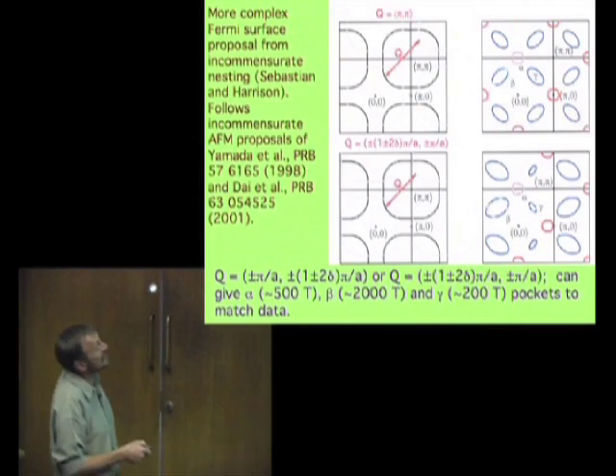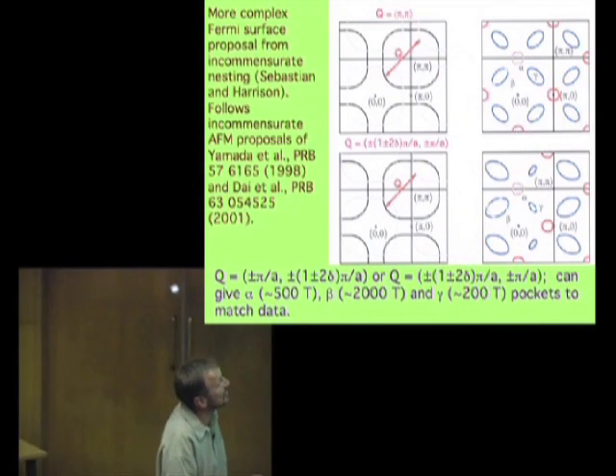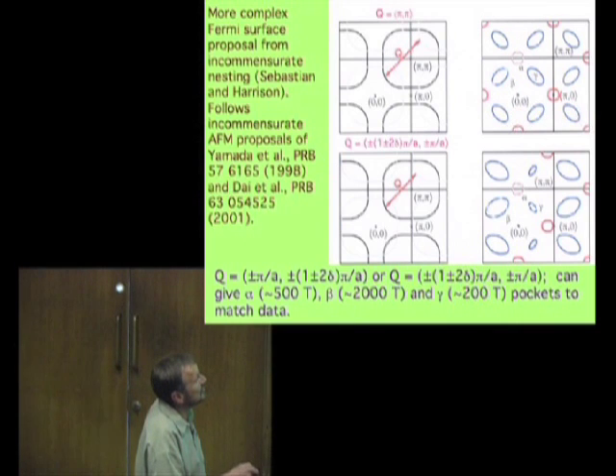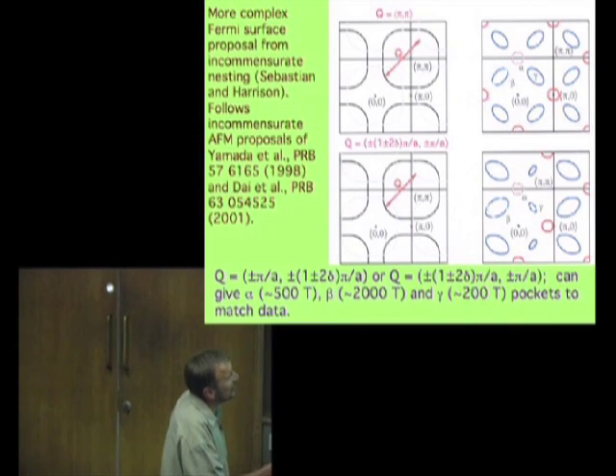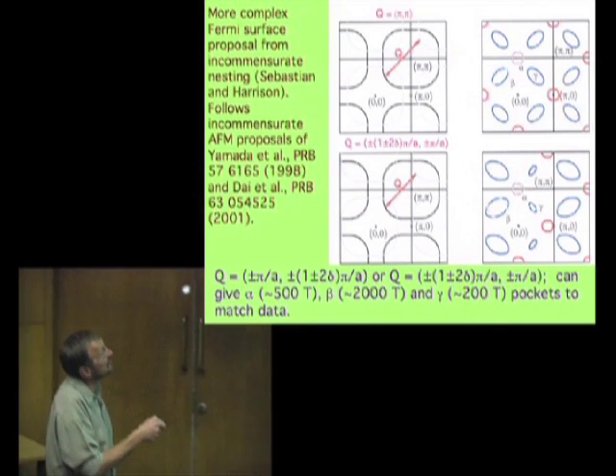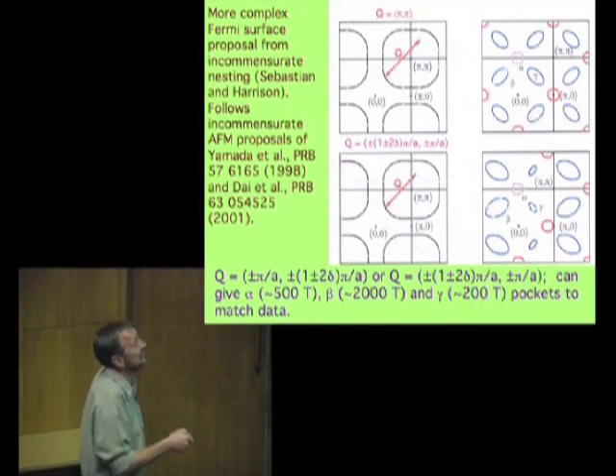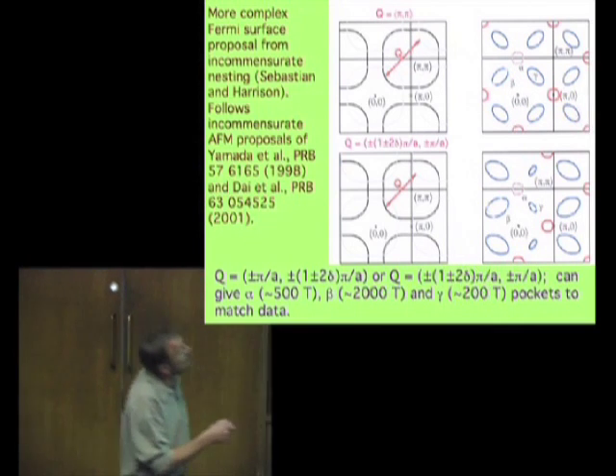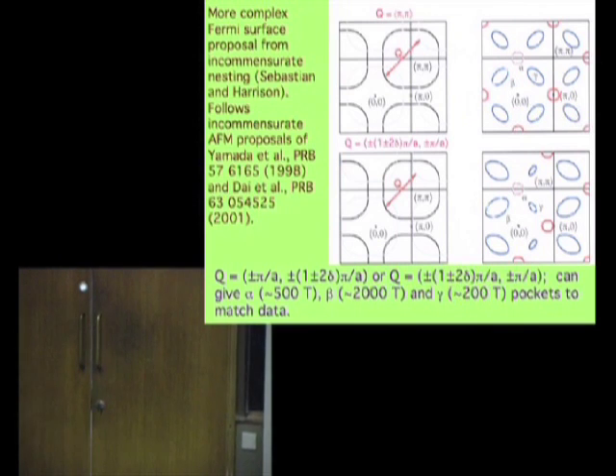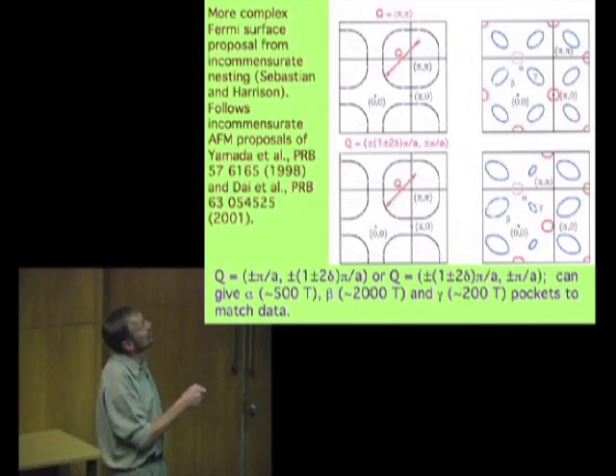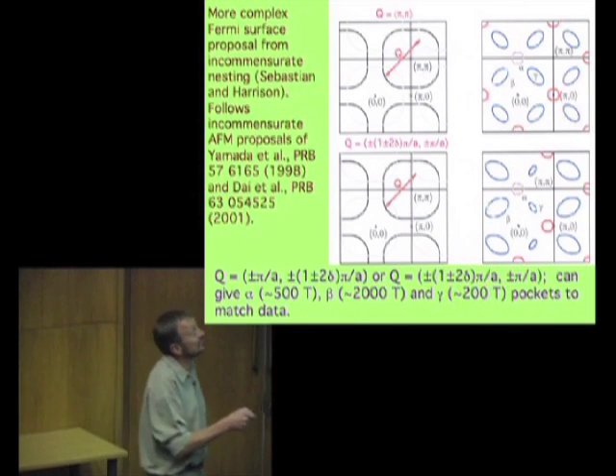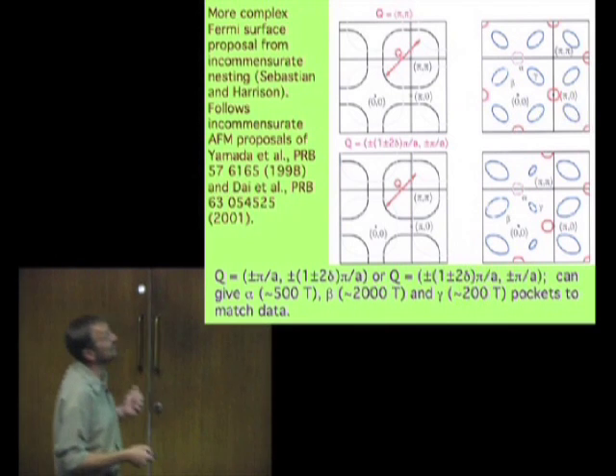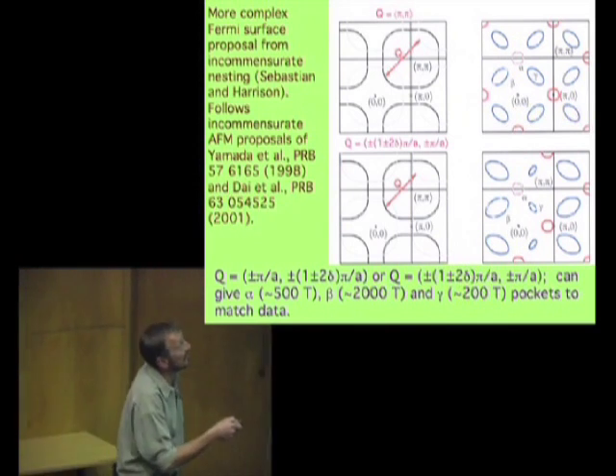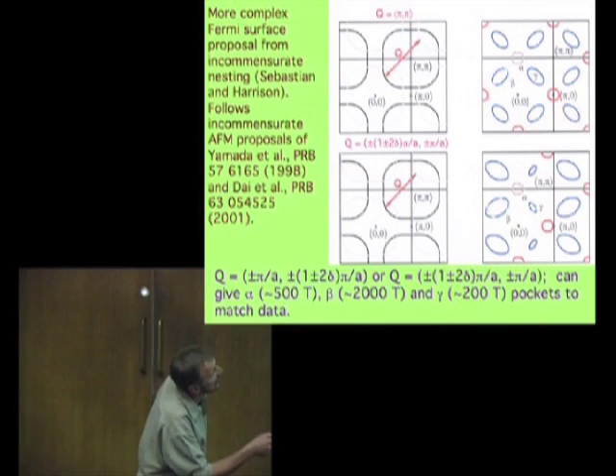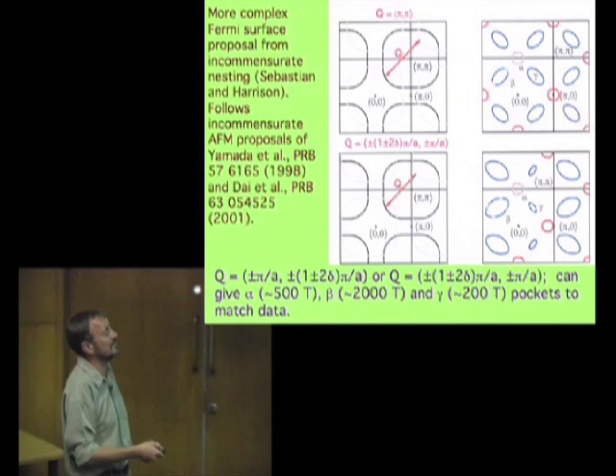Now it turns out that to replicate our Fermi surface, the thing that we actually measure, with its three different pockets, alpha, which was the 500, 600, 700 Tesla one, beta, which was the 1500, 1800 Tesla one, and gamma, the one which was responsible for the low frequencies, you have to propose quite a complicated wave vector for the distortion. But it turns out that this wave vector is seen in neutron scattering measurements. It's seen in antiferromagnetic scattering, and it's an incommensurate antiferromagnetic wave vector. It means that the antiferromagnetism has a different periodicity than the real space crystal does. And that gives us this new K-space periodicity, which gives us a mapping of the original Fermi surface to create the thing that we actually measure in the measurements.